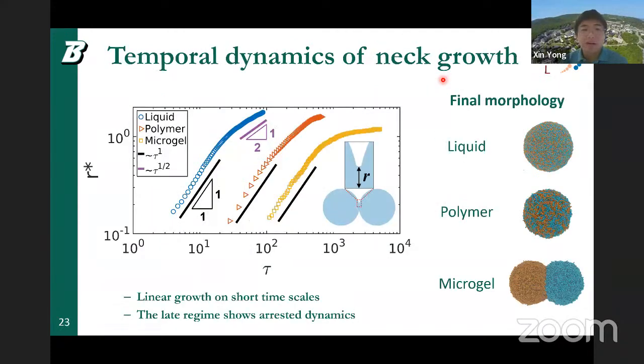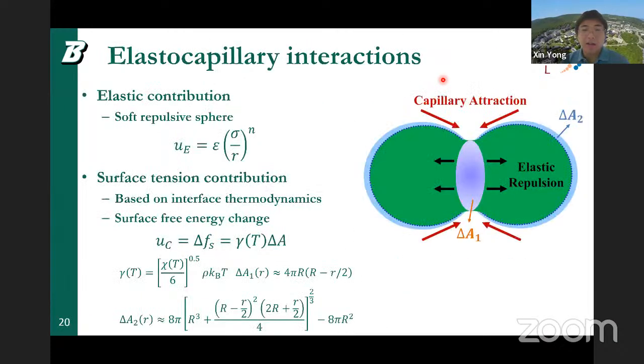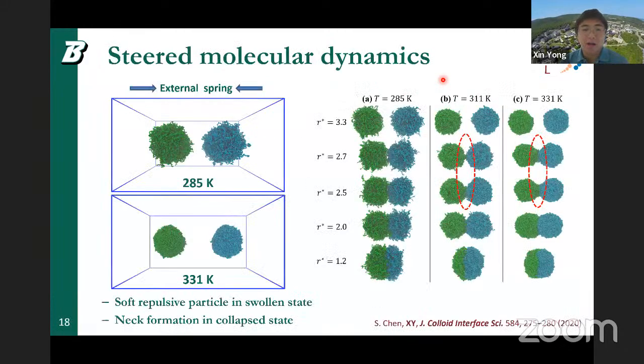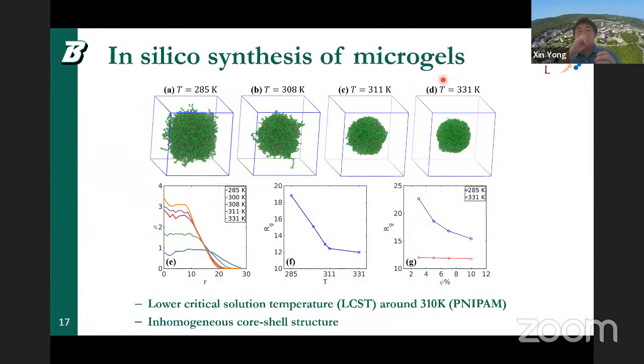That's a great question. This goes back to how we actually make these microgels. I mentioned it a little bit, but it was probably too quick. The way we generate this microgel is a little different from some other approaches. The old approach is that you create a regular network structure with constant polymer strand length, for example a diamond or cubic lattice, put the cross-linker at the lattice points, and then make the chains between them. That's a very common way of making microgels. But here we adopt a different one.